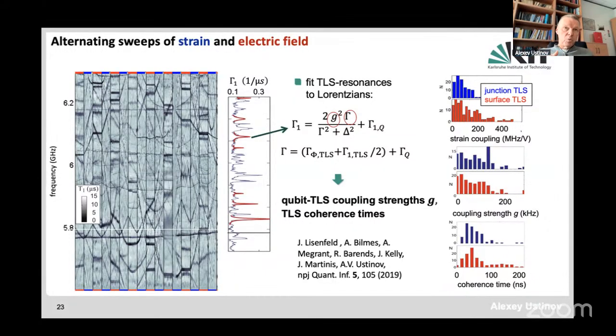operation of the qubit. When you excite the qubit from the ground state to the excited state, you apply a voltage across a capacitor, which is simply a dielectric of a thickness of the order of 1 to 2 nanometers. And the electric field there is large. Therefore, these defects can be strongly coupled to the alternating electric field, and they show strong coupling strengths up to several tens of megahertz.